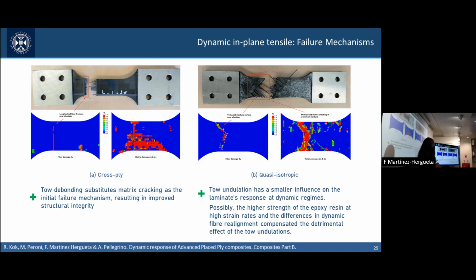So these are more or less the samples and the failure modes. Of course, the main failure mode is fiber failure. There's also quite a lot of matrix cracking, but there is a slight difference in failure modes and how they are triggered that results in an improved response. The first one might be a slightly higher strength of the epoxy resins that might delay the matrix cracking that was occurring. But there has to be also a difference in the dynamic fiber realignment.